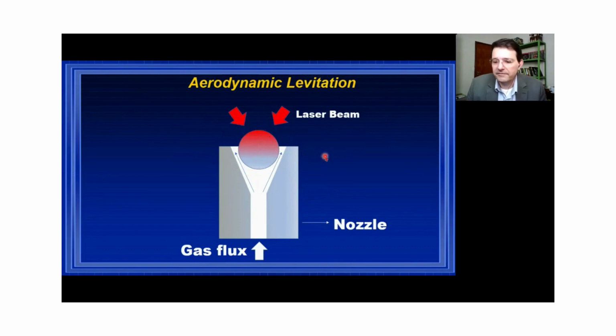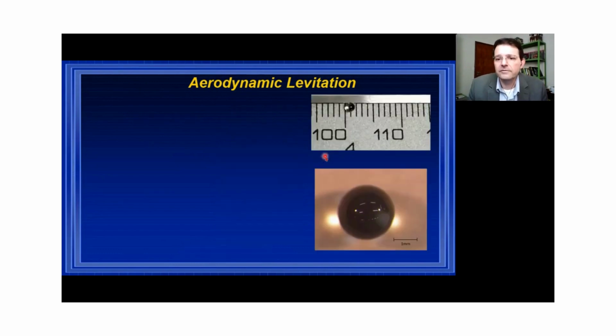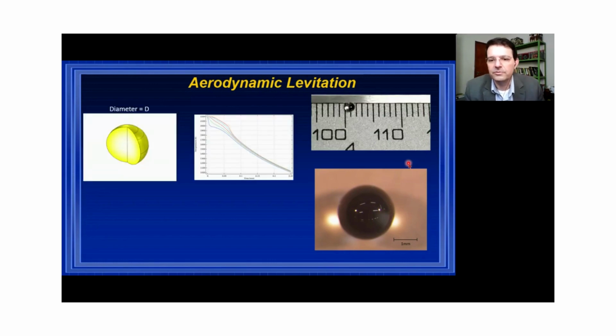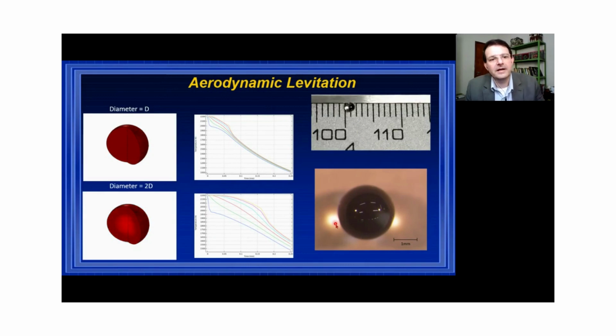If you cool this very fast, then you can make a glass of it. So you can see here, we have a sphere about 1 millimeter in size, with a natural fire polishing of the material, see? It's already polished for you, so you can make a measurement. You can see here the focus of the flashlight. So it's quite good optical quality. And of course, if you have a larger diameter, you have a smaller cooling rate, right? If you have a small diameter, you have a fast cooling rate.